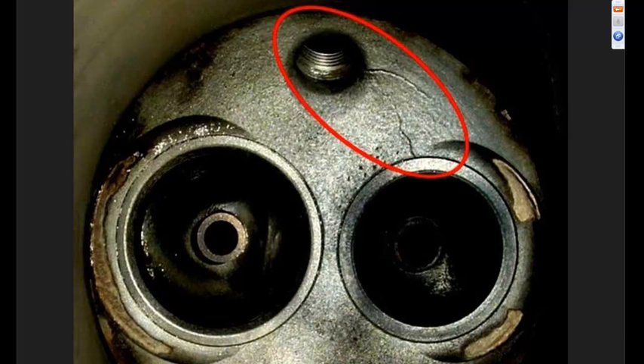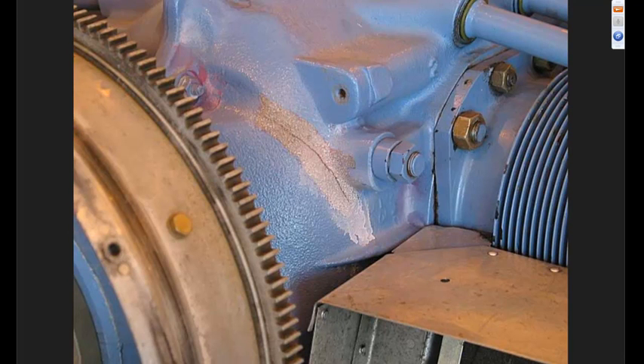This one looks pretty expensive. This is one of the nastier crankcase cracks that I've seen. I've seen a lot of crankcase cracks, but this one's pretty bad. This was on a Lycoming engine, obviously, and the pink color again is from dye penetrant that was sprayed on the surface of the crankcase in order to make the crack more apparent. But that's a pretty good sized crack. That looks like it was probably a 3 or 4 inch long crack. So that engine definitely is not going to be flying for a while.